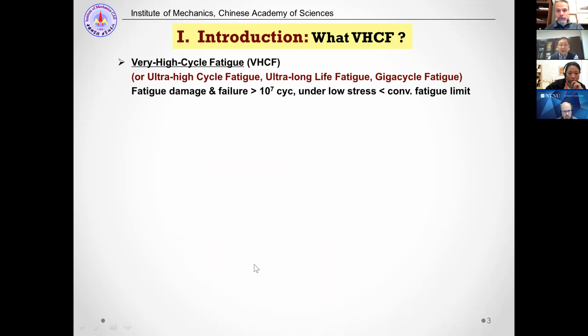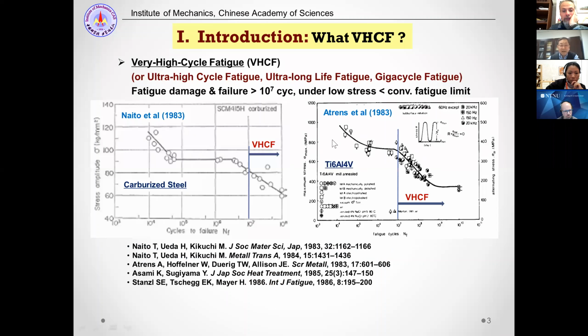In the beginning, I would like to mention briefly what is very high cycle fatigue. Very high cycle fatigue is fatigue damage and failure beyond 10 to 7 cycles of loading, and the applied stress is quite low, below conventional fatigue limits. And here are two early examples showing the very high cycle fatigue cases for high strength steel and titanium alloy. And we can see this part beyond 10 to 7 cycles of loading, and also here beyond 10 to 7 cycles of loading, very high cycle fatigue regime.